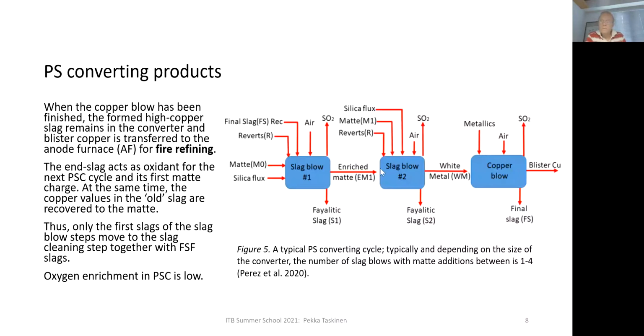So this kind of step-wise approach to the anode furnace and blister copper, depending on the size of the converter, produces a few hundreds of tons of blister copper. Oxygen enrichment in PS converters in these steps is low. It's a few percent only, 5 probably, not about 10% anyway.